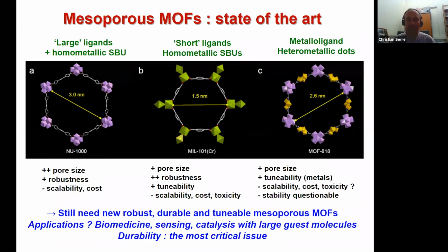And of course, why do we need mesoporous material? Maybe it's a naive response, but if you want to deal with large guest molecules, for instance, or RNA encapsulation, or if you want to introduce some inorganic nanometer-size nanoparticles for catalysis. And when you want to design this mesoporous material, the stability issue, which is already a critical parameter when you make a microporous MOF, becomes even more critical. So the durability, the stability under operation is even more critical.